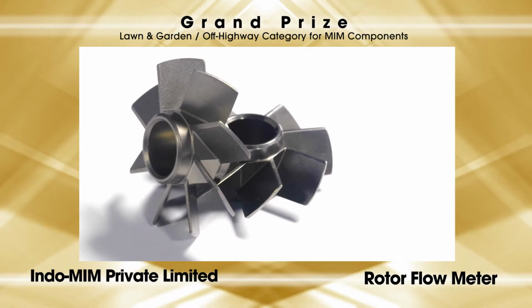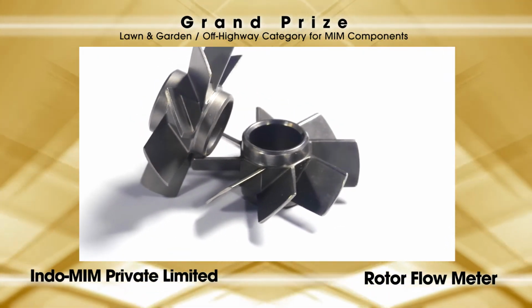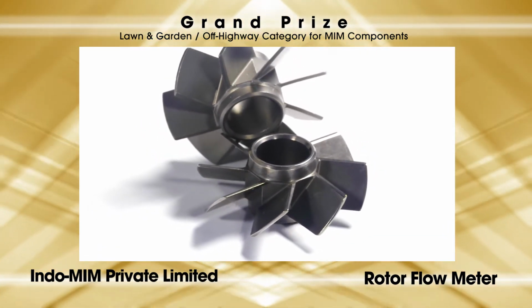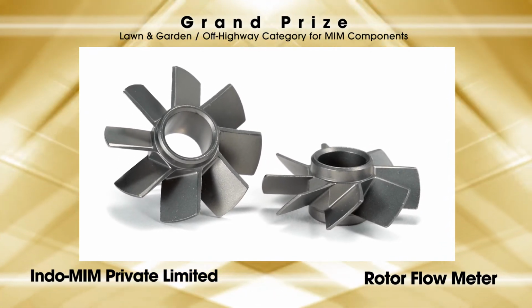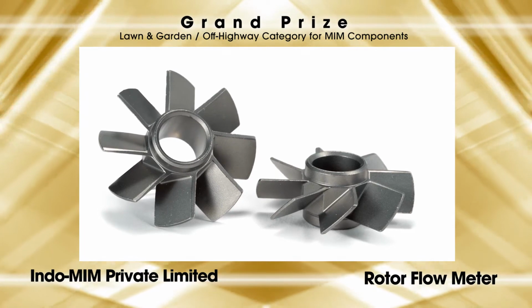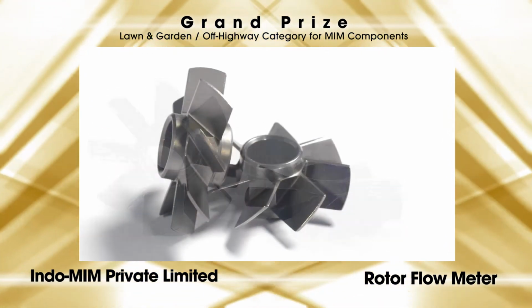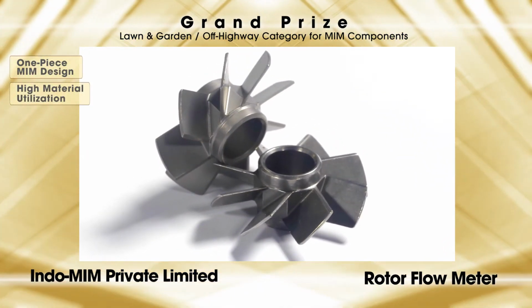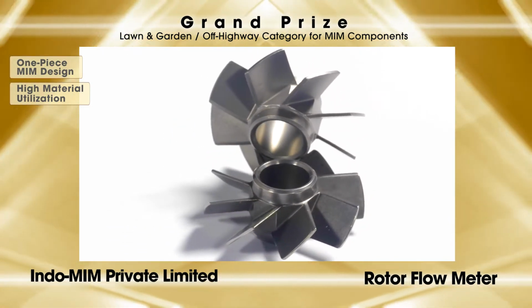A diaphragm gate at the center was provided for uniform filling. Since the positional tolerance of the blades with respect to the central hole is important, special staging was used for sintering to produce the part without distortion. The outer diameter is 32.9 plus or minus 0.03 millimeters with a positional tolerance of 0.02 millimeters and a thickness of 6.5 plus or minus 0.05 millimeters. Previously machined, MIM provided a one-piece rotor consistently at a substantial cost savings, and all sprues and risers are recycled and reintroduced into the process.